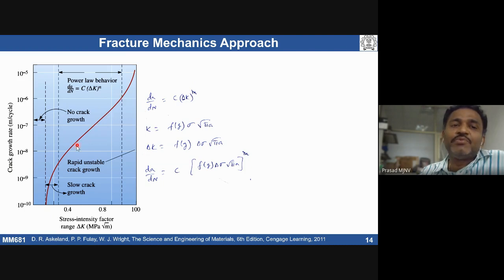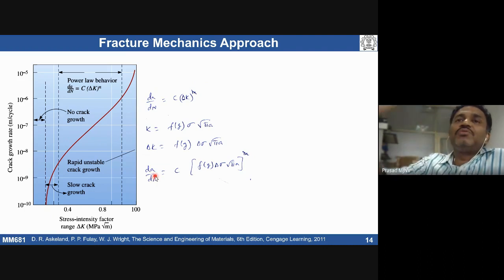The crack growth under cyclic loading conditions is going to depend on the stress intensity factor range to the power of M. M is the Paris exponent, C is a coefficient. So if I want to know dA by dN, I put this delta K here, to the power of M. Now if I want to know how many cycles are required for the crack to propagate from a certain length to a certain length.